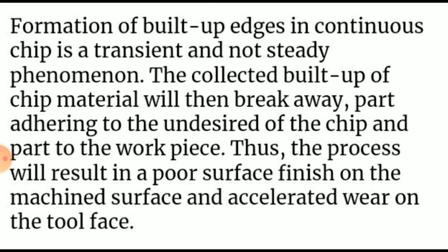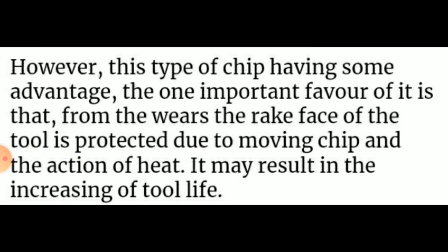Thus, the process will result in a poor surface finish on the machined surface and accelerated wear on the tool face. Low cutting speed also contributes to the formation of built-up edge. Increasing the cutting speed, increasing the rake angle, and using cutting fluid reduces or eliminates the built-up edge.